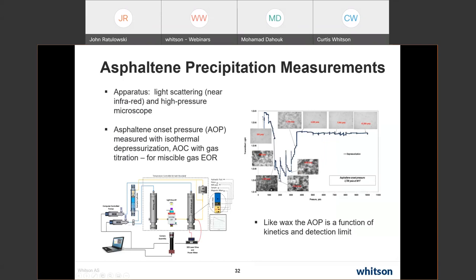Like wax, the AOP is a function of kinetics and detection limit, and there's a lot of literature on this. The asphaltenes probably have a much wider range of kinetic impacts than even waxes, and so sometimes it's very difficult to get your hands on the actual real thermodynamic boundary because the kinetics make a huge difference. And low asphaltene fluids, again, they may be unstable. Even though there's a very small amount of asphaltene, they do cause problems, and that has been seen in the field. But actually measuring the AOP for a low asphaltene content fluid is very, very difficult.